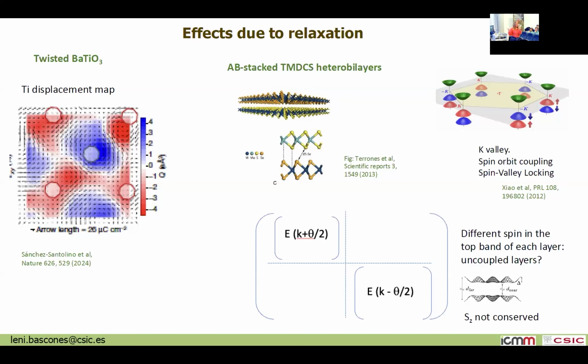For the dichalcogenide you can do multi-orbital models. In fact, that's easier for them. But for example, for one of the layers it will be mostly a spin up, and for the other layer it will be mostly a spin down. There is in reality some spin texture, but in the twisted bilayer, the spin is degenerate. So you can build the models, and you just have to be careful with all these details when you build the model. In the transition metal dichalcogenide, you don't have the spin degeneracy, so you only keep one of the bands. And if it's not conserved, what I mean is that you have an effective orbital that is a bit mixed, and all the tunneling is just through the relaxation.